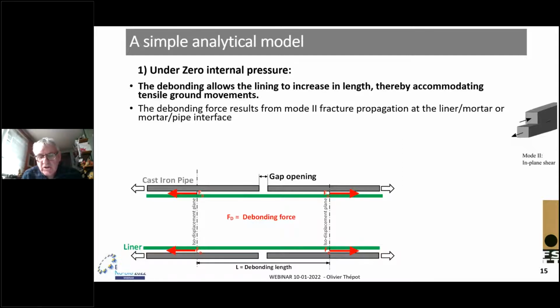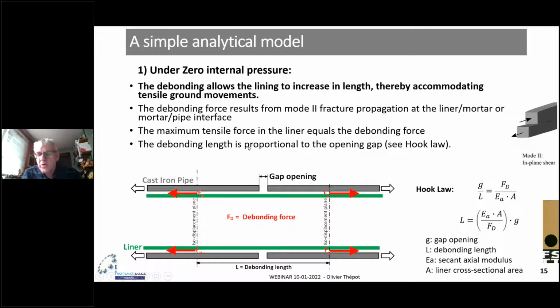Under zero pressure, the tensile force in the debonding area equals the debonding force. By using Hooke's law, it's easy to show that the length of the debonding zone is proportional to the opening gap. It's the formula on the right. To avoid failure of the liner, the debonding force must be less than the ultimate axial strength of the liner. It's a stability condition.